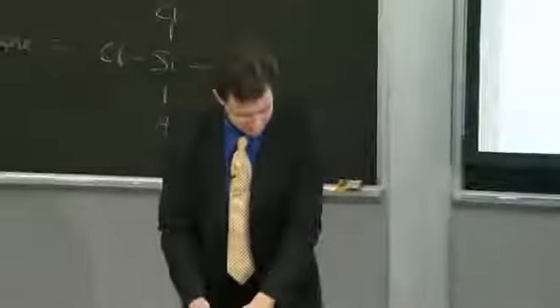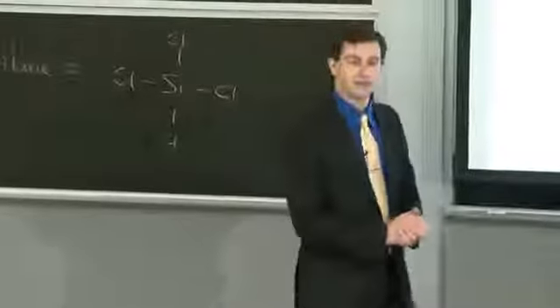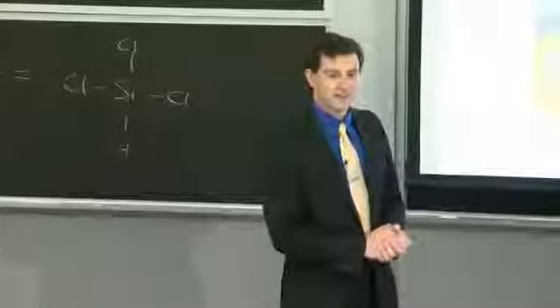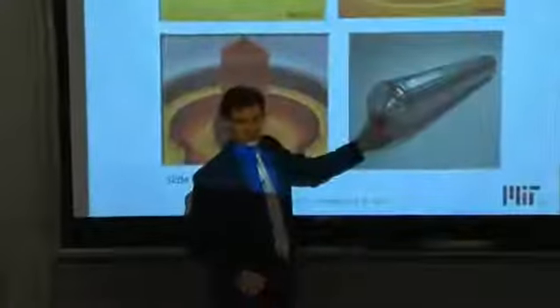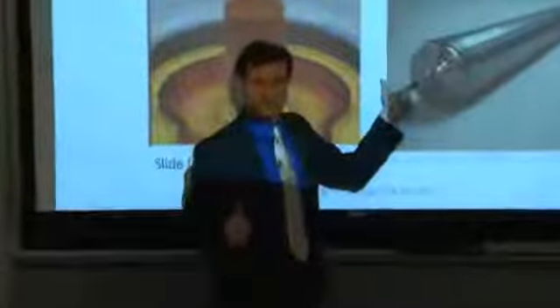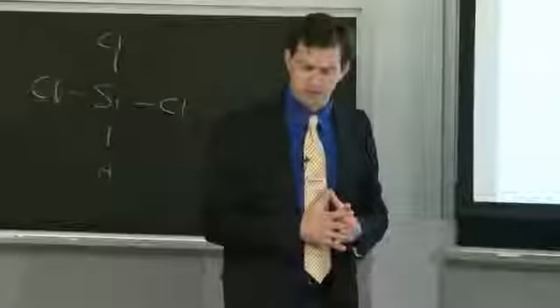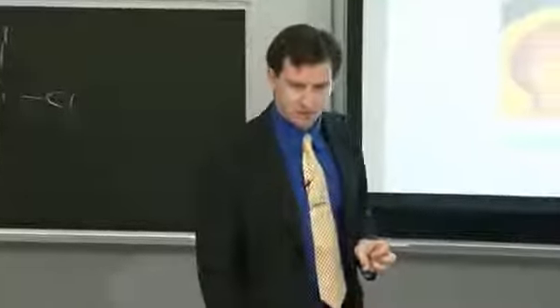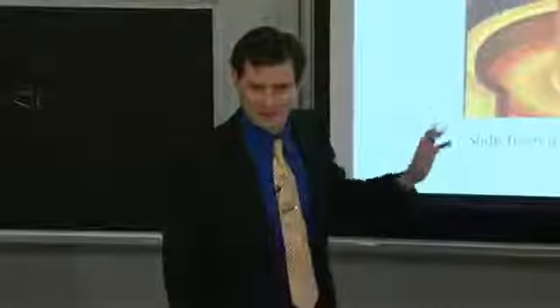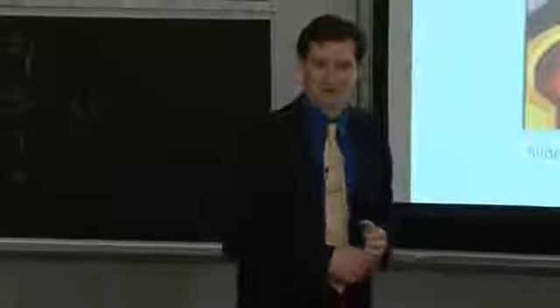Does the seed rod extend all the way through the ingot or just near the top? All right, so the entire ingot becomes patterned or templated by the seed rod. So this entire ingot has the same crystalline orientation as the seed. And is the seed doped differently than the resulting ingot? It might be, but I'm not aware that it affects the overall process. It could be that it's one of the critical pieces of the magic sauce that makes it work, but I'm not aware.